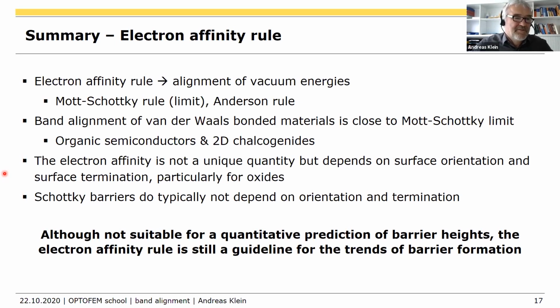If you have a polycrystalline material, every interface is in principle also single crystalline. So you have grains with different orientation, but along the grain, this is like a single crystalline interface. And the question is, if you have one grain and another grain, whether the barrier here or here is the same. And as I explained before, it usually does not differ. So a polycrystalline material is not necessarily something with defects. It becomes a little bit different when you look at these perfectly epitaxial two-dimensional oxide heterosystems, where you can say that this is definitely something without defects.